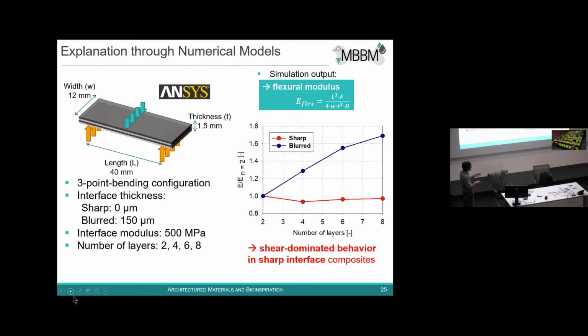What is happening actually is that in the simulations, what we accounted for is shear behavior. So when you have a very sharp interface, there is a transmission of stresses which induces a lot of shear in the soft layer. And so the stiff layers deform, there is a lot of shear deformation between the stiff layers induced by the soft layer, which is not present when there is a blurred interface. So this is a little bit of a didactic example to show the impact of such interfaces, even in a very simple geometrical arrangement like this multi-layer composite.